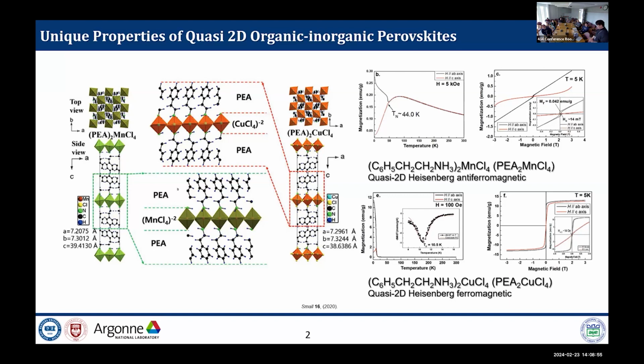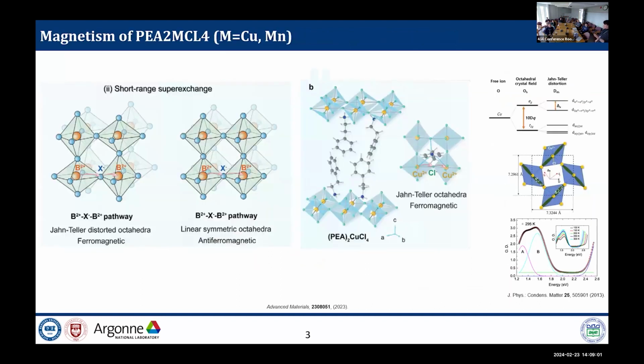So, okay, let's look in more detail at the magnetic origin of this material. In PEA2 copper tetrachloride, this is a quasi two-dimensional Heisenberg ferromagnet. This magnetic ordering comes from the structure, in which the copper tetrachloride octahedra are distorted by N-H...Cl hydrogen bonding. It makes a D4h distorted octahedral state and causes a Jahn-Teller distortion. You can see the NH3 and N-H...Cl hydrogen bonding and the distorted system. As in the figure, with only the copper ion, the d orbital energy is the same, but in the octahedral Oh state, the d orbital energy splits into two different energies, Eg and T2g.